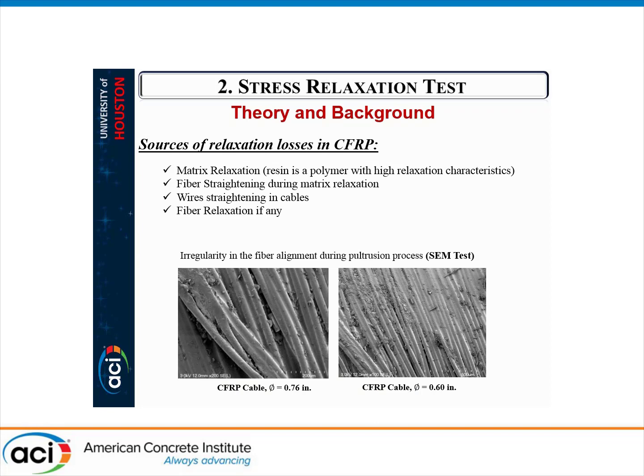Another important aspect of the study is to understand the sources of relaxation in a CFRP composite. So we have the main sources of relaxation. First is the matrix relaxation, which is happening in a relatively short period of time after applying the load. And then we have the fiber straightening, which is due to misalignment in fiber orientation in the composite.